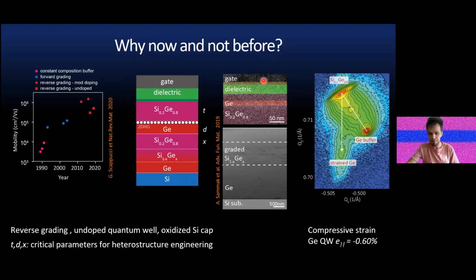Here are a few experimental results from our first quantum wells, where you see, of course, a TEM section of the virtual substrate. Here, a nice and uniform quantum well, nice and flat. And here with X-rays, we actually measure the strain in the quantum well and see that it's exactly how we designed the quantum well to be. So that means we have full control over the heterostructure growth.